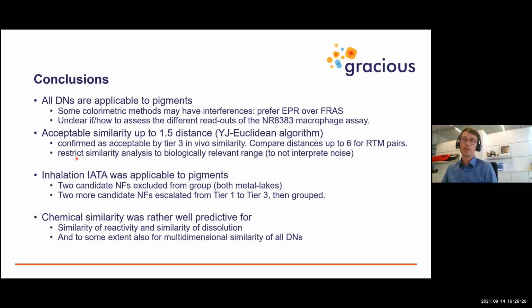We did restrict our similarity analysis to the biologically relevant range, and that turned out to be very important, because otherwise we would interpret noise, or we would interpret irrelevant differences, such as what I mentioned, the difference between 500 and 700 days halftime. So the IATA was applicable.